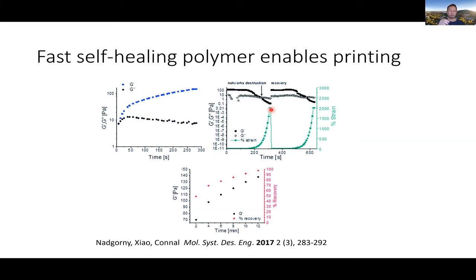So we essentially break it by shear on the actual instrument. And you can see here, we get pretty good recovery very quickly. So this is minutes. We can actually get almost 100% of our material's properties back very quickly. And so that's really key for something that can break and reform these bonds quickly.